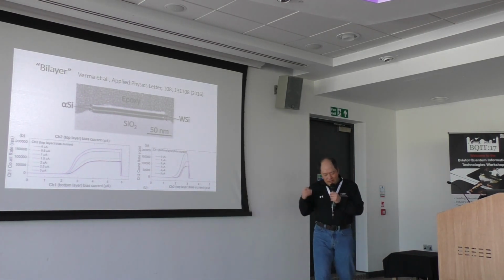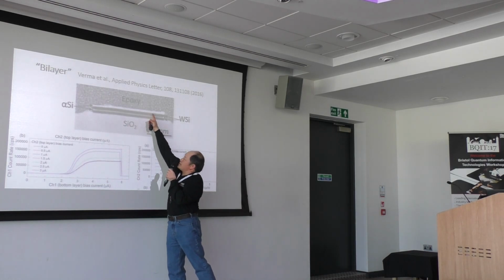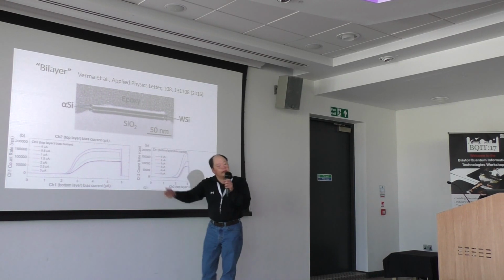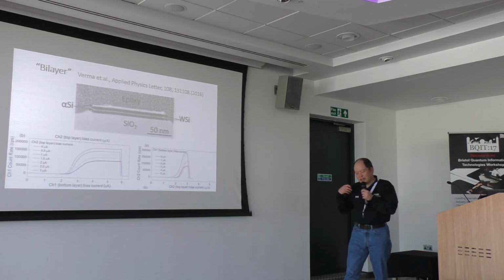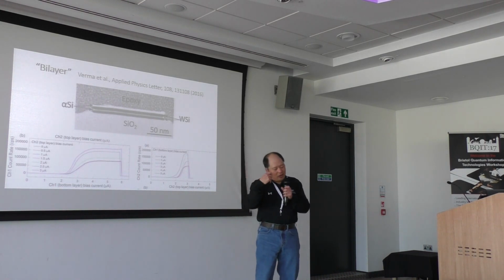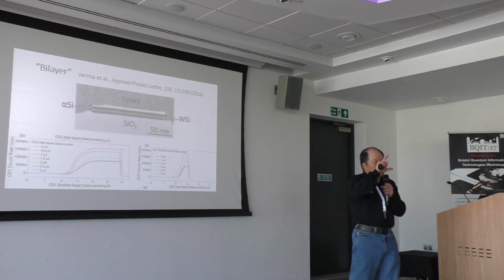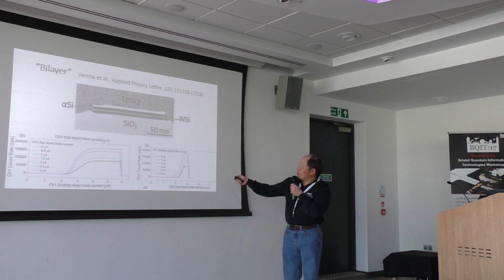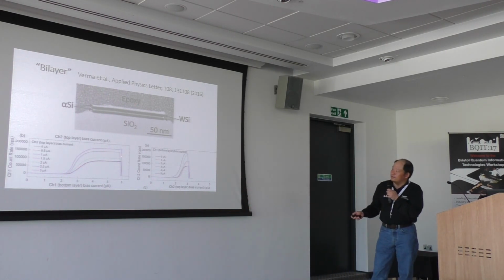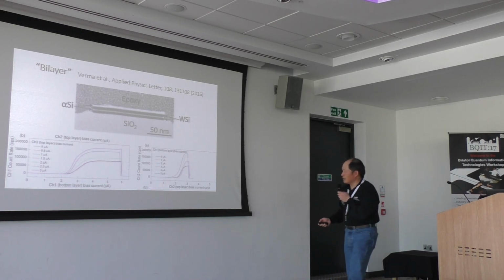And so what you can do is stack different nanowire detectors together so that if you get energy deposited in one layer, the heat can translate to the other and break the superconductivity in both layers. You can effectively make thicker stacks of this nanowire material. When you think about it from an optical design point of view, oftentimes a variable you'd like to adjust, if you're really optimizing the stack of materials to get really high efficiency, is the thickness of the absorbing region, because it could turn out when you do the optimization that slightly thicker detector material will give you higher efficiency. So that's something we were able to try to do. This is an example of the count rates that we saw in, say, the top layer nanowire device as a function of current in the bottom layer and vice versa.